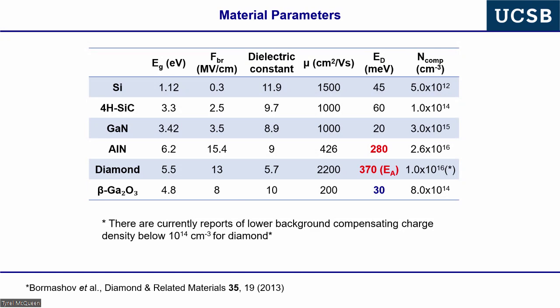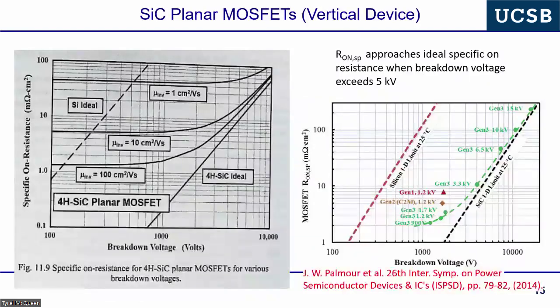In gallium oxide, you're able to experimentally pull this information out and see it, but you don't have a solution to see which site. Honestly, I don't think experimentally we know which site. I'm sure folks with much better crystal chemistry intuition can make a very educated guess. I can't. Okay, I can't. But there are definitely two sites.